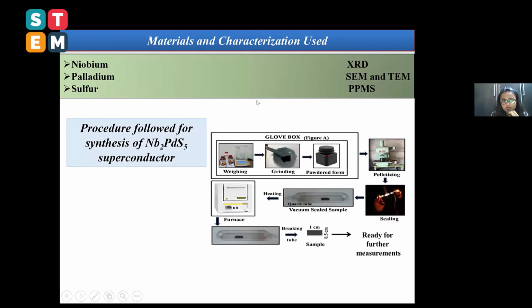This is the procedure followed for synthesis of the Nb2PdS5 superconductor. First, we weigh the elements niobium, palladium, and sulfur in a stoichiometric ratio, and then we grind this material using a mortar and pestle into powder form. Then we pelletize the powder using a pelletizing machine in a glove box, and then we seal the material in a quartz tube. After sealing, the sample was kept inside the furnace to complete the reaction.